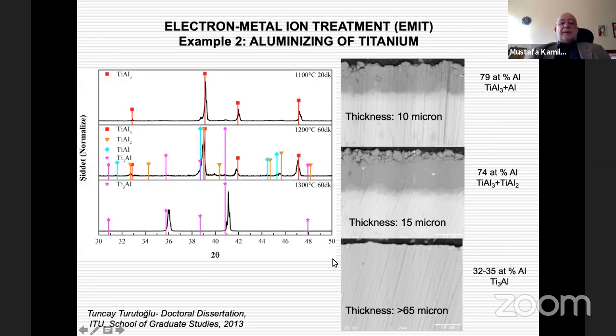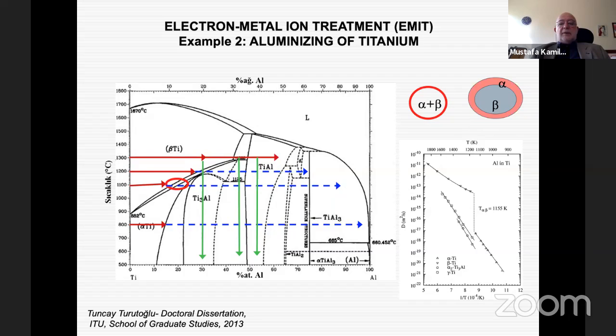And then when we increase the temperature further to 1300 degrees, we see a tremendous increase in the diffusion rate of aluminum into titanium, and we end up with a surface layer that has an aluminum content around 30%, extending beyond 65 microns. So this is an interesting story and needs to be explained by the knowledge of physical metallurgy and diffusion. When you look at the binary phase diagram of the titanium aluminum system, and also at the diffusion behavior of aluminum into titanium, you see interesting things taking place.